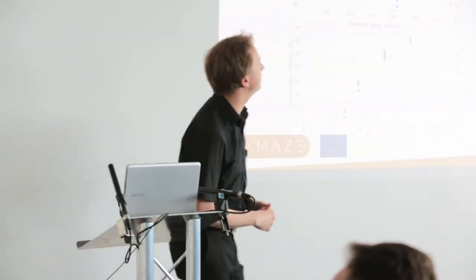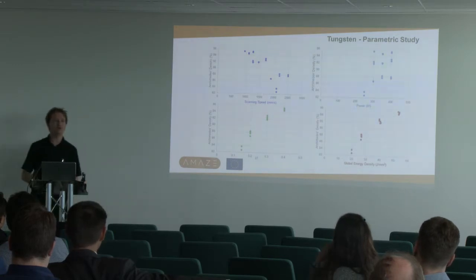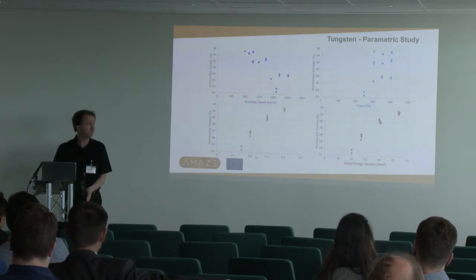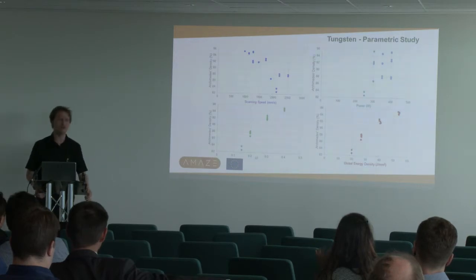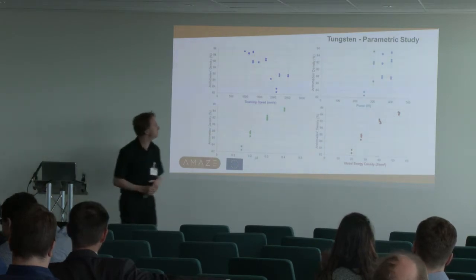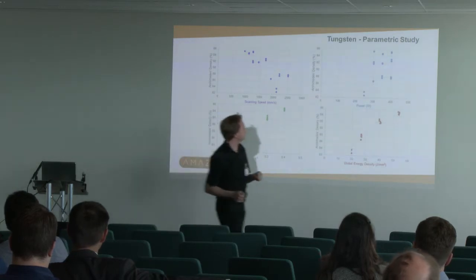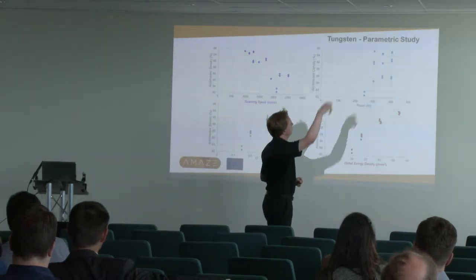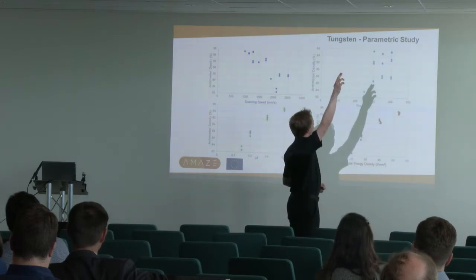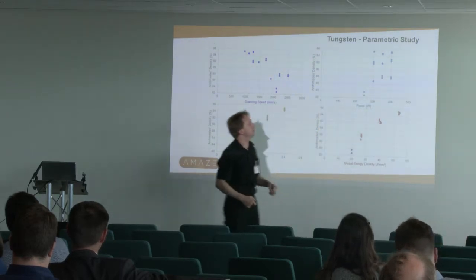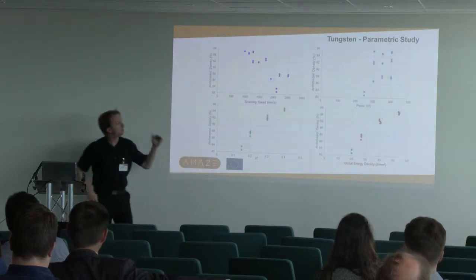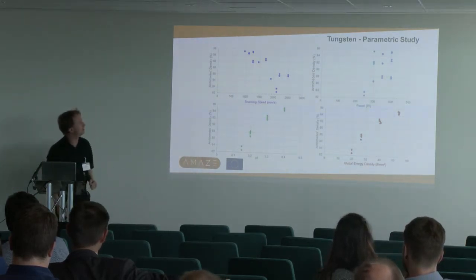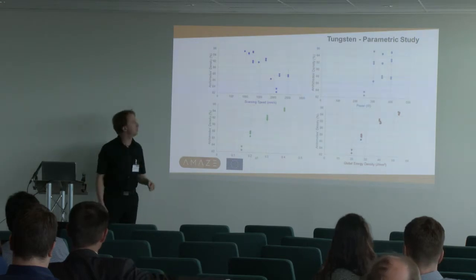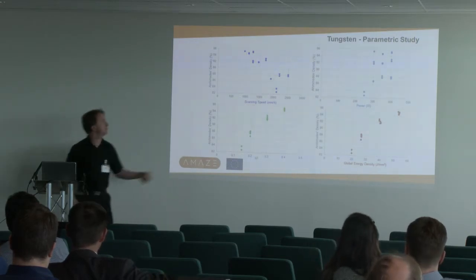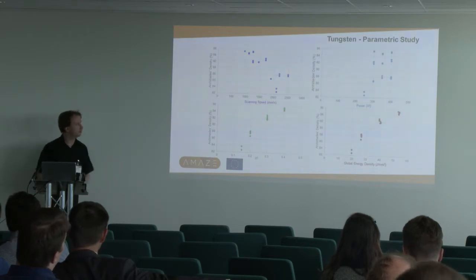So all the points here, these are different plots, but of the same points. All the points here were processed under the same volumetric energy density. But you can see there's a huge variation, so it's not necessarily appropriate for this material. On the power side of things, you're seeing a threshold at about 250 watts, but beyond that, it's basically showing that power is not really having such an impact after that 250 watt level. The trend goes downward with scan speed, as you might expect. The faster you scan, the more porosity, or the lower the density of the material.